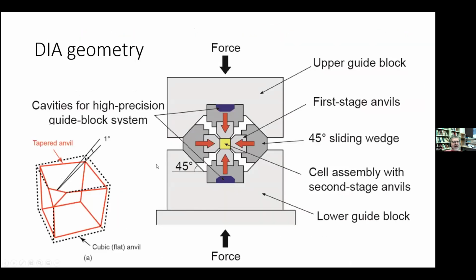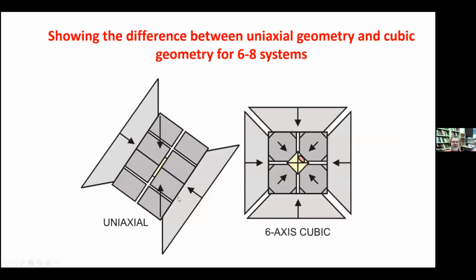So that's a tapered anvil, like I mentioned. This is how the taper is. Actually, Ito developed that in Misasa a long time ago, but this is pretty much the same as what Ito was doing when I was there to make perovskite, but now using harder carbide and using this specially aligned geometry. So the first one is the uniaxial, and this is what that geometry looks like from the side. It's basically two axes pushing, and the somewhat uneven forces mean you can't do the ultra high pressure with it. This is the 6 axis with the forces equalized on all 6 axes, so that you can do high pressures without breaking the anvils.